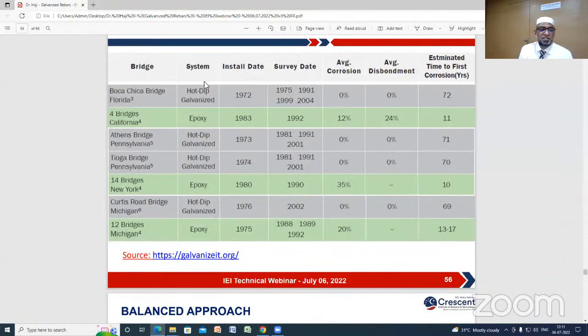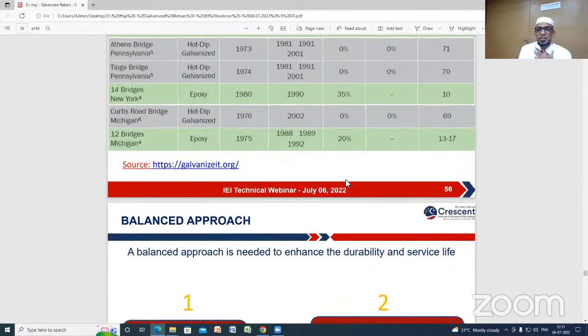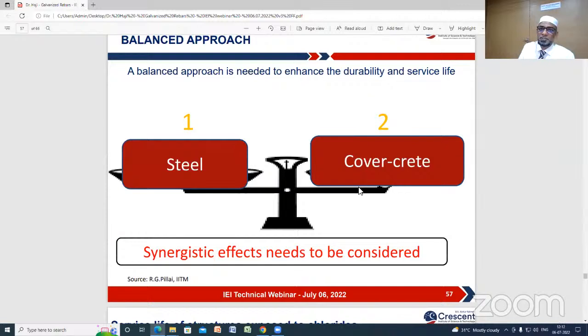These are other statistics. In the Boca Chica Bridge, they used galvanized rebar in the year 1972. They did corrosion surveys in 1975, 1991, and up to 2014, and they didn't find any corrosion. So again, another example of hot dip galvanized rebar employed in 1972, still doing well. In the case of other coated rebars, they found even up to 35% corrosion initiation or corrosion rate. So this research work clearly indicates that if you use galvanized rebars, definitely the durability of the RC structure will improve.